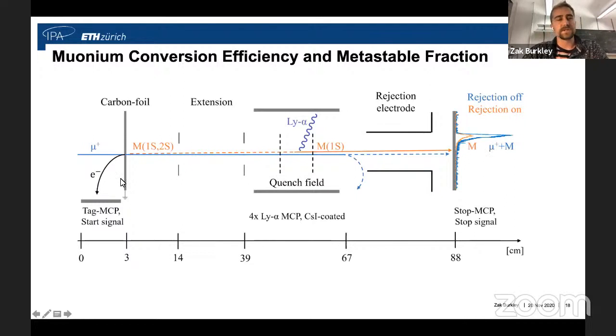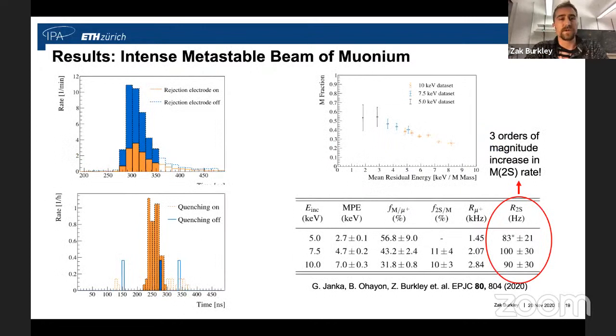So what we were able to determine was, one, the amount of muonium that is converted as the muons go through this carbon foil is a function of the incoming muon energy. And then two, with the quenching field and Lyman alpha detector, how much of that muonium was in the metastable state. And so I'd like to show those results now.